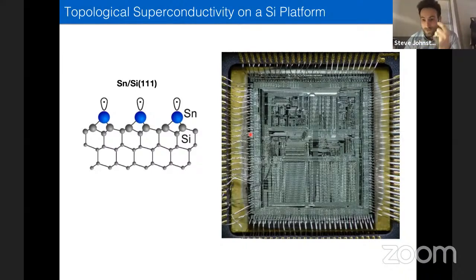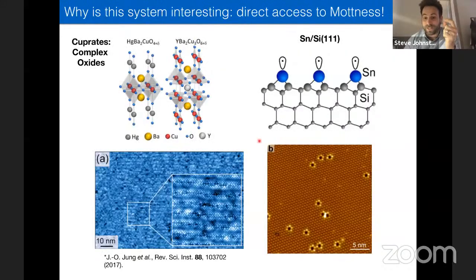What I really like about the system, though, is that, as I showed you at the very beginning, it's a very clean system. I know that some people in the audience have worked on QPI and tunneling in cuprates. In those systems, your tip often has to tunnel through these rock salt structures in order to get to the copper oxide plane. So it's an indirect pathway for the tunneling electrons. And the QPI or real space density images are often riddled with inhomogeneities. There have been long discussions in the community of whether these are intrinsic inhomogeneities, but there's always a bit of concern that some of it may be coming from stuff that's happening off plane, right? The impurities are off the plane, atomic structures that are off the plane, and so forth.